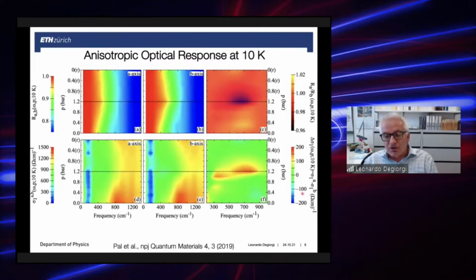And you see, in fact, that at an energy scale around 60 millielectron volts, so very close to the Fermi level, you get a stress-induced anisotropy, which goes back to the initial state. So it is fully reversible upon tuning the external symmetry breaking field. Now, after I tried to convince you at least that at that low temperature there's a stress-induced anisotropy, let me